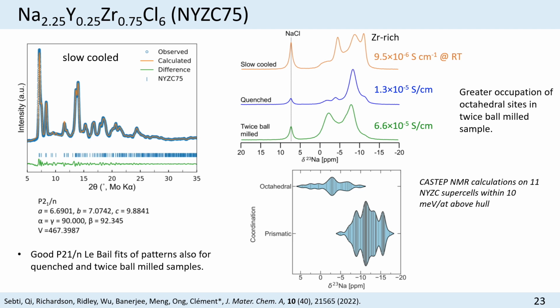This is a depiction of results from our first principles calculations of NMR shifts for sodium in prismatic sites in the crystal structure and in octahedral sites. Here we're using a violin plot to depict the distribution of these chemical shifts. But what this is telling you is that if you have a prismatic sodium, you'd be between -5 and -17 ppm, which is about this range of shifts. So these chemical shifts are likely due to sodium in these prismatic sites. And then if you're in this region, around here, you've got sodium in octahedral sites. So what that suggests is that you have a change in the population of the sodium sites and you're occupying more of the octahedral sites as you ball mill.